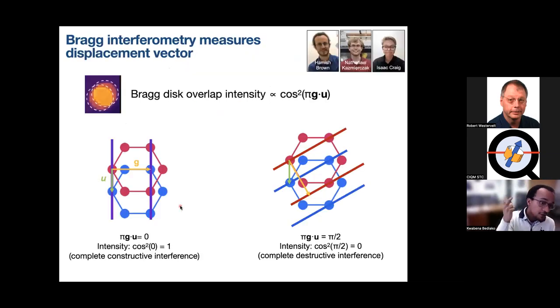And the consequence of this idea of displacement vector is that the overlap intensity, when these beams from the two Bragg disks overlap, they are either going to constructively interfere or destructively interfere. And the intensity of the overlapped region is given by this function here, where you have this dot product between the graphene reciprocal lattice vector and the displacement vector. And so you can envision that for this case of a saddle point type stacking, you expect complete constructive interference between the two scattered electron waves for one reciprocal lattice vector, and complete destructive interference for this reciprocal lattice vector.